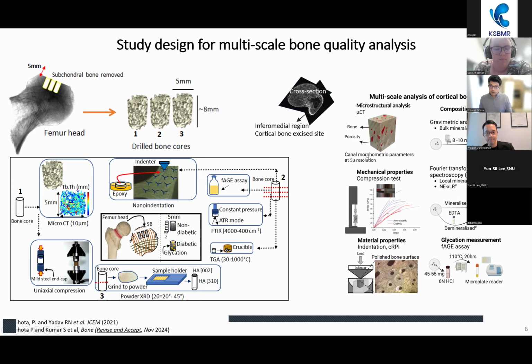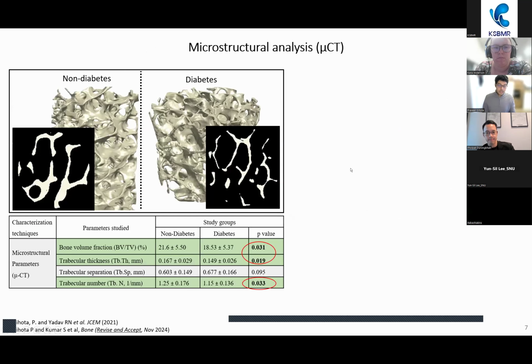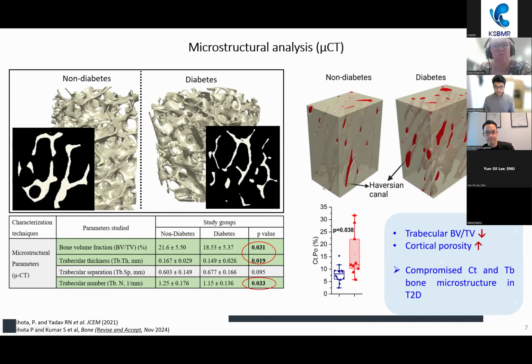The same was done with cortical bone analysis: microstructure with micro CT, compression test, material property, and small scale compositional analysis and FAGE assay. So the results say that we have low bone volume fraction in trabecular bone because of lower trabecular thickness and trabecular number. And we found increased cortical porosity in the diabetes cohort. So overall, cortical and trabecular bone microstructure is compromised in type 2 diabetes.